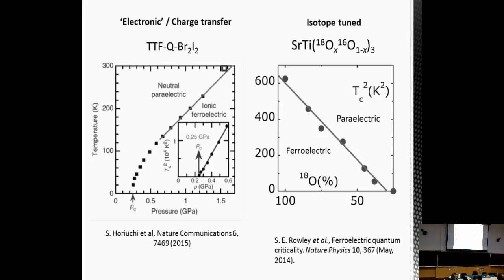And then finally, we have a case of isotope tuning to reach a quantum critical point. So in the case of strontium titanate, you can change the oxygen-16 isotope for oxygen-18, so just adding 2 extra neutrons in the nucleus. And that's enough to push the system from being an incipient ferroelectric to being a long-range ordered ferroelectric with a transition at 25 Kelvin. And then by changing the percentage of oxygen-18, you can tune that down to a quantum critical point.